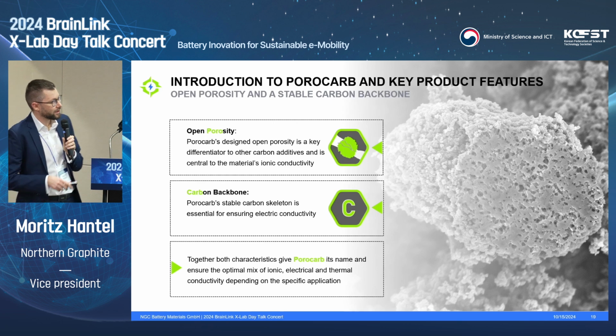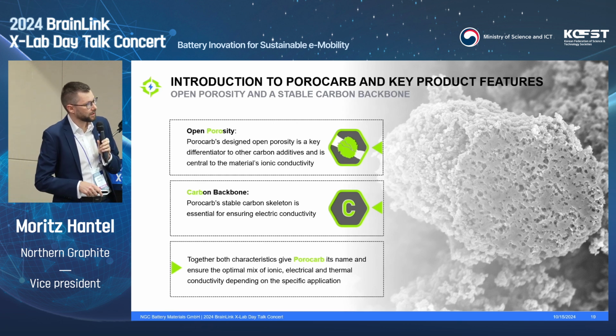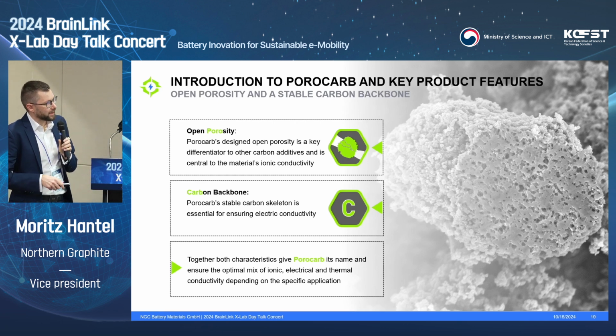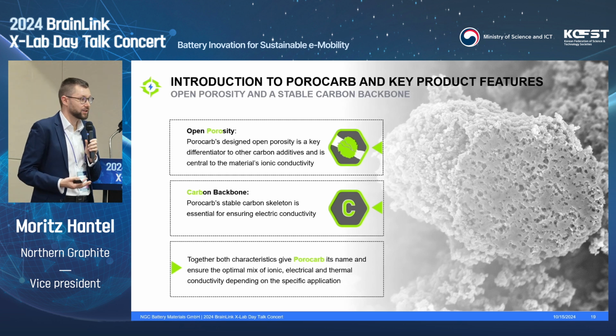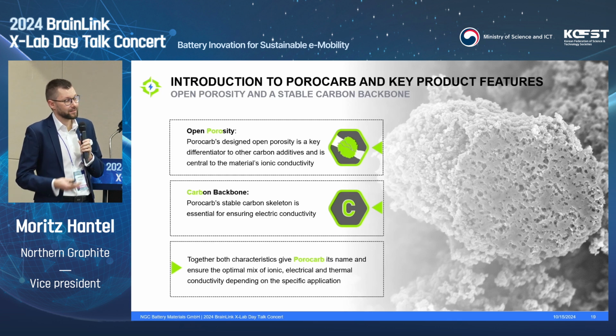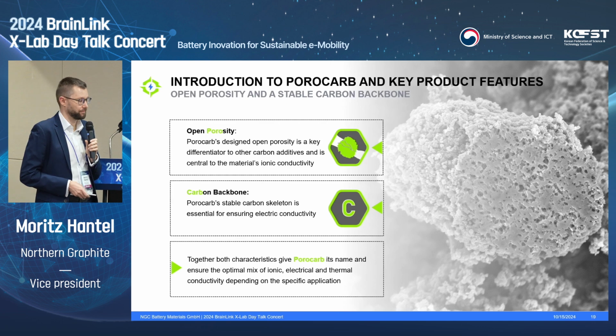And you can see here on the right side an example with a FIB cut, where you see the open inner porosity in the particle. This enables, in the application, a pathway for electrolyte, a local electrolyte reservoir, and therefore enhances, besides electric conductivity, especially the ionic conductivity.